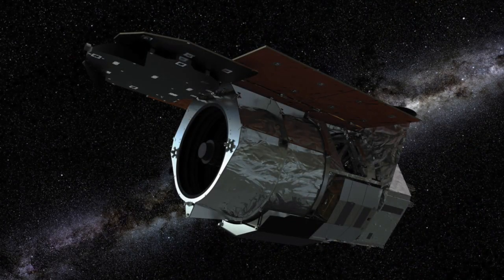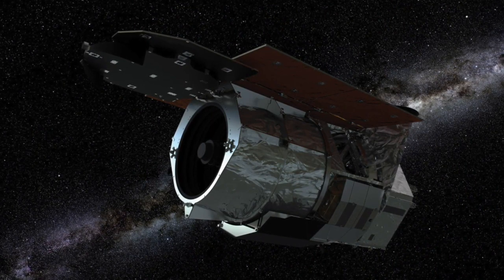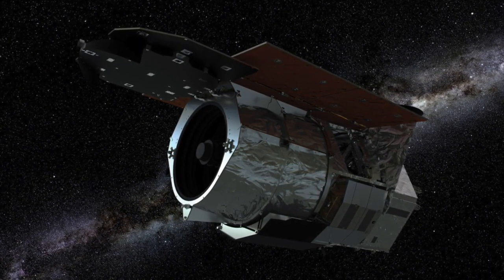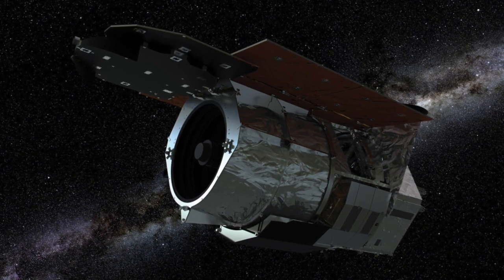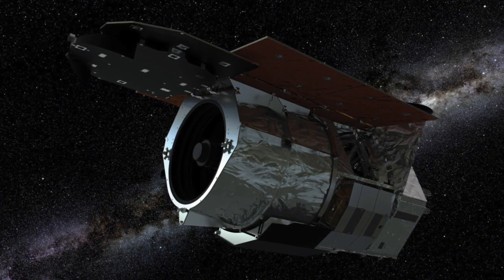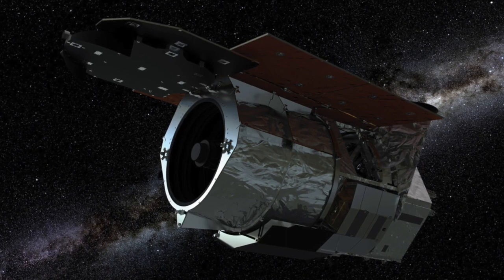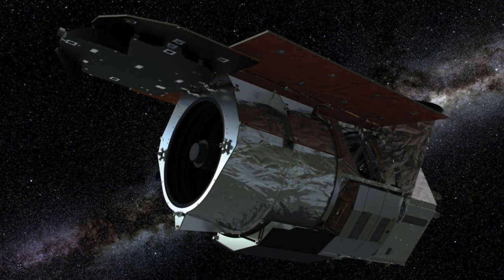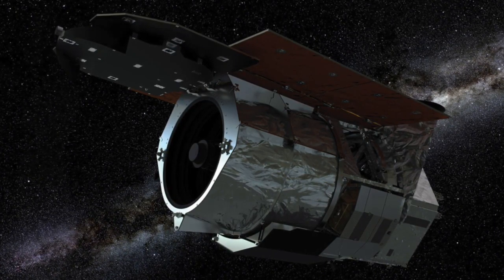When light strikes at right angles to a superblack surface, less than 0.35% is reflected back, 7 times less than from black paint. At greater angles, the advantage increases. At an angle of 45 degrees, superblack reflects 25 times less light than black paint. It's especially useful for coating parts of instruments that must be kept cold, such as infrared space telescopes, because unlike ordinary paint, it doesn't crack at low temperatures.